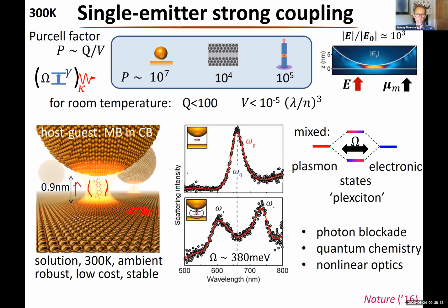When we do that, we can look at the scattering. This is the scattering, and it's nicely around 650 nanometers of just the empty CB. So we remove the dye molecule, and we can see these very nice scattering spectra. That's our cavity mode. And then when we put the dye in there, which is vertically oriented, we can see that we get this very nice, strong splitting. It depends on how many dyes we have in the gap, that this splitting varies. So what's happening is that we start off with a molecular electronic state, a HOMO-LUMO dye state, and we're coupling it to this plasmon, and that coupling is so fast that we create this anti-crossing here. These are sometimes called plexciton states.